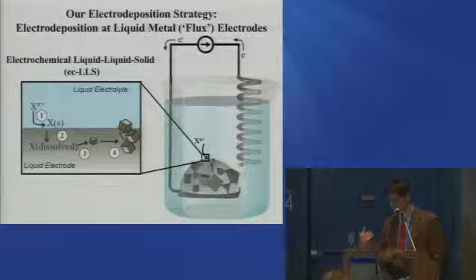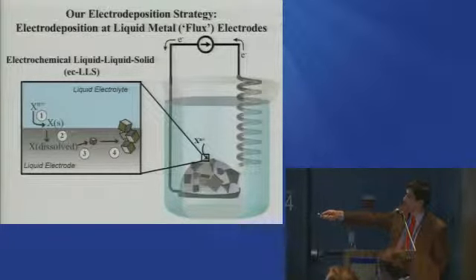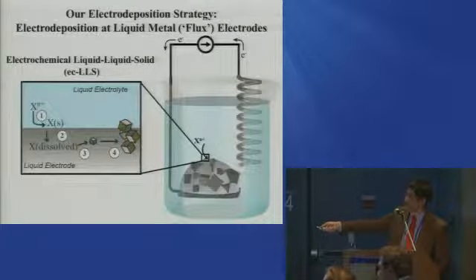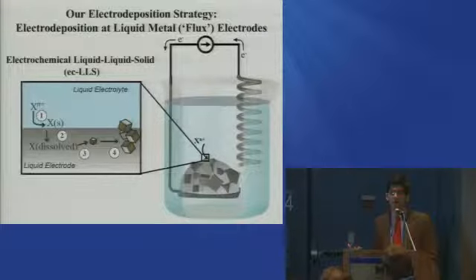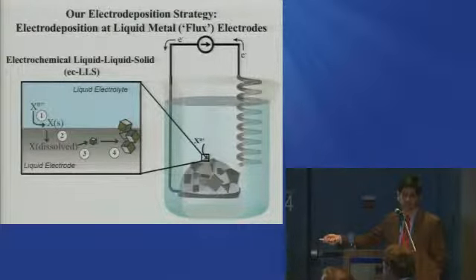And the gist of it is this process, which harkens back to the days of early electroanalytical chemistry, but we sort of refined it and we call it an electrochemical liquid-liquid-solid crystal growth, where the idea is you can electrodeposit some semiconductor on the surface of a liquid metal electrode, but this liquid metal can act not only as an electrode but also as a solvent. Whatever you deposit on the surface can dissolve in this liquid metal, and you can form a solution.